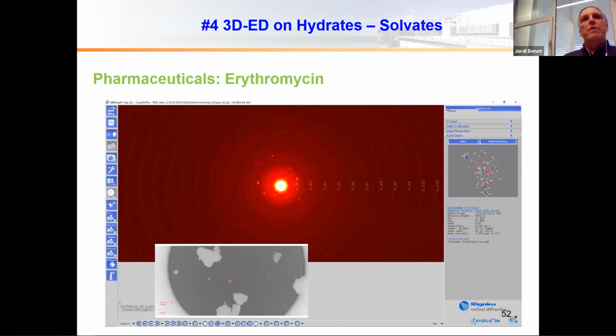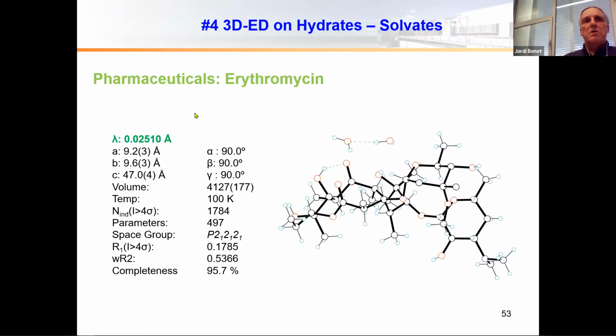Just in the morning, we prepared the ELSA, we mounted the crystals, and we measured 3 crystals, and the 3rd crystal diffracted, and we could solve the structure. This is this small crystal here, you can see. So this is around, let's say, in the big size, around 300 nanometers. In the thinner side, it was probably like 20 or 30 nanometers.